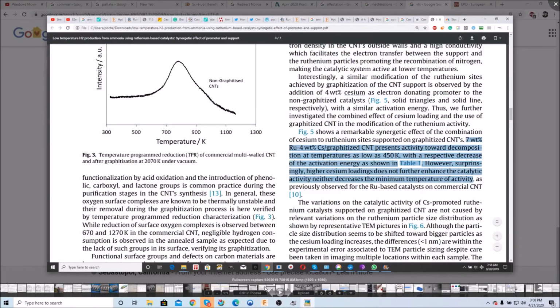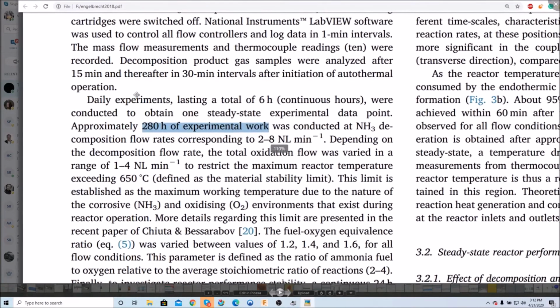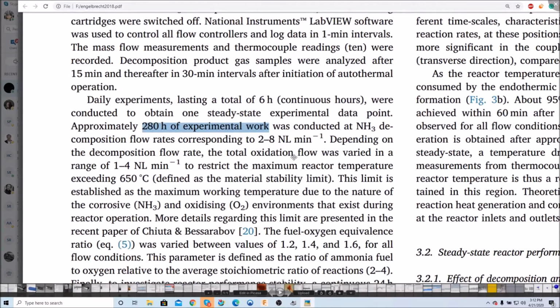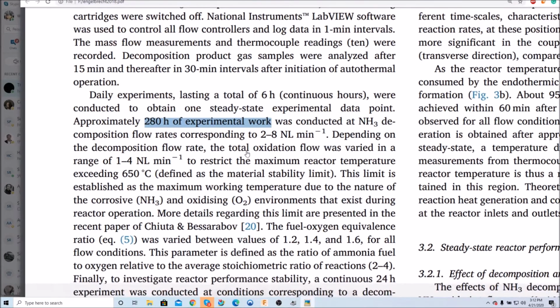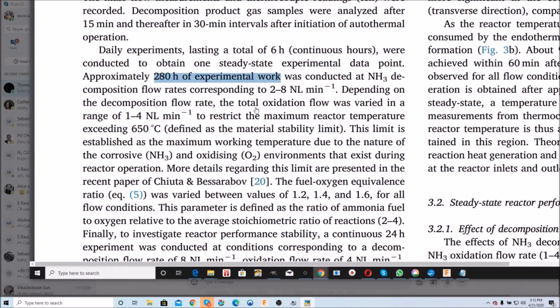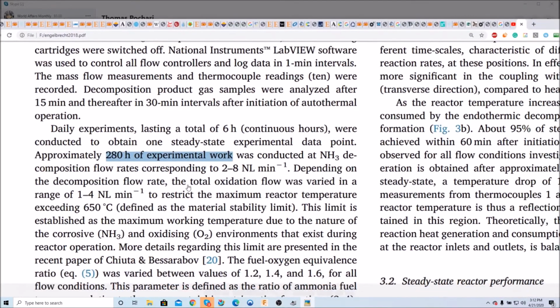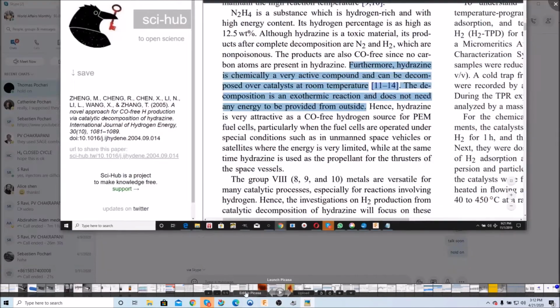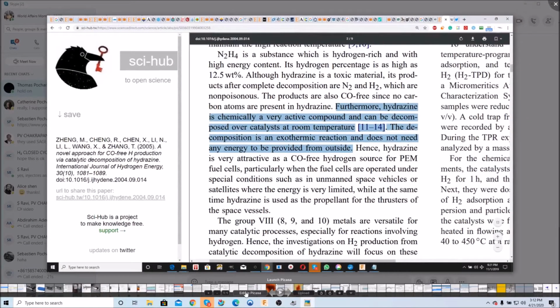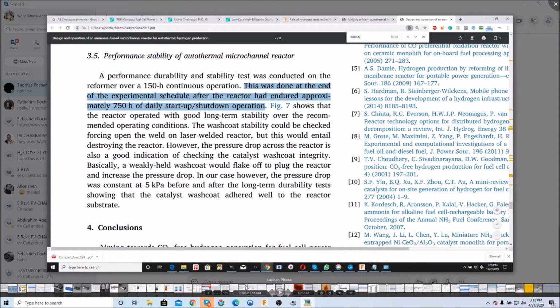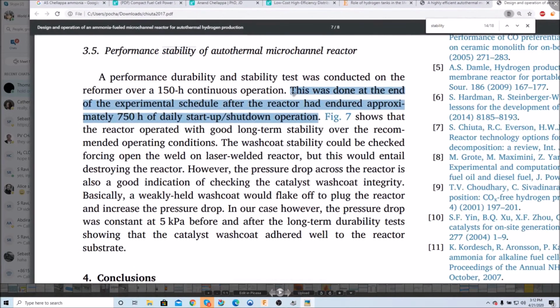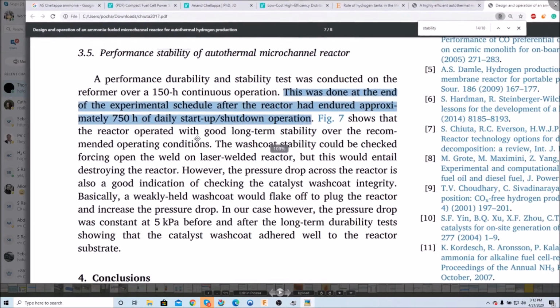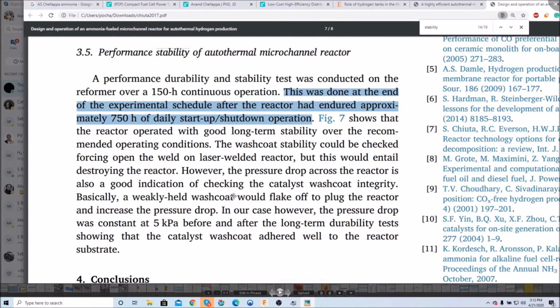And then I'll go over the longevity of the catalyst. So 6-hour continuous tests, approximately 280 hours of experimental work, found minimal deactivation during this period. So 150 hours plus another 750 hours. The reactor had endured 750 hours of daily startup shutdown operation. This shows that the reactor operated with good long-term stability over the recommended operating conditions.